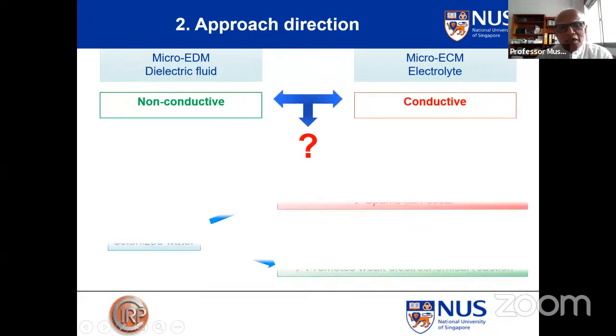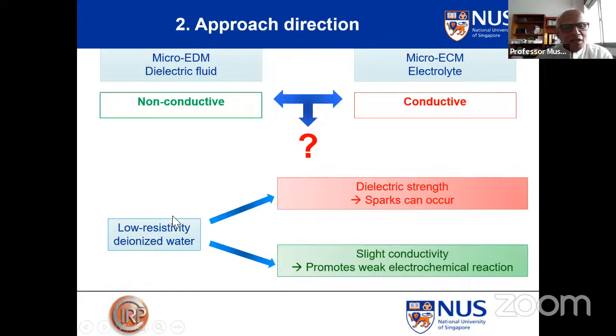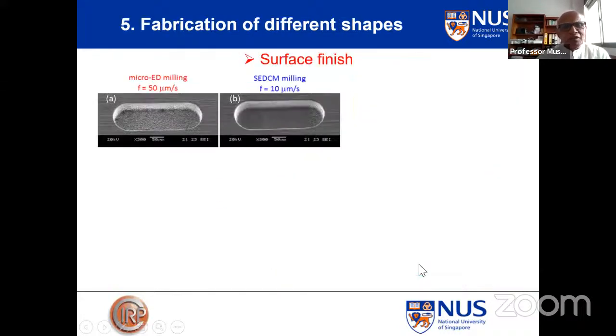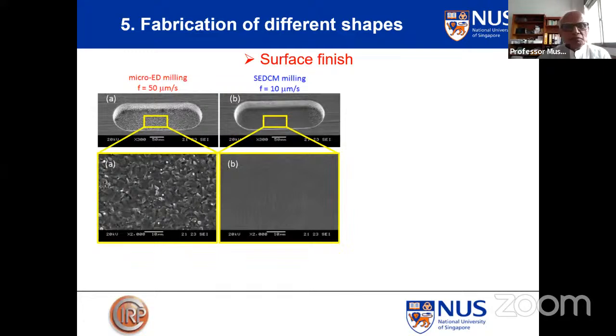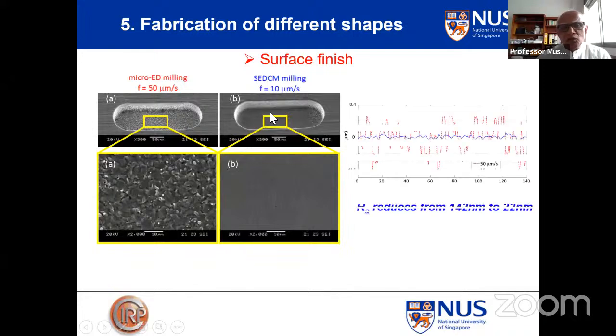Again, I will skip those details. We have done it using low resistivity deionized water, where the dielectric strength is good enough to do sparking and the conductivity is good enough to do ECM. And finally, I show the surface. In normal EDM, the bottom surface is rough, but when we compound them together, hybridize, then you get a surface finish. It's actually a nano surface finish.